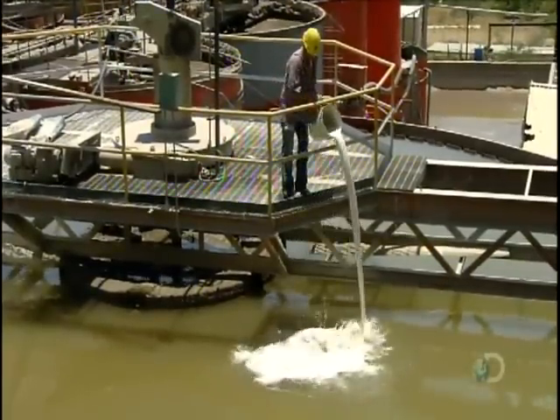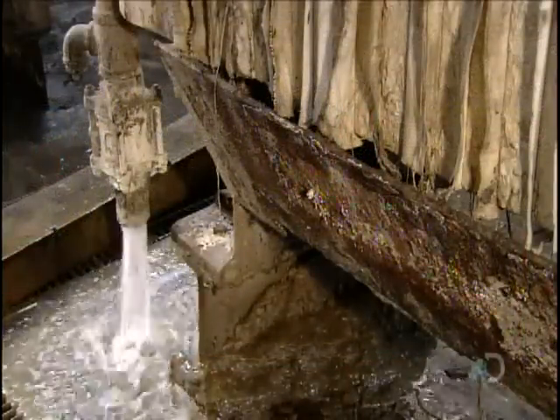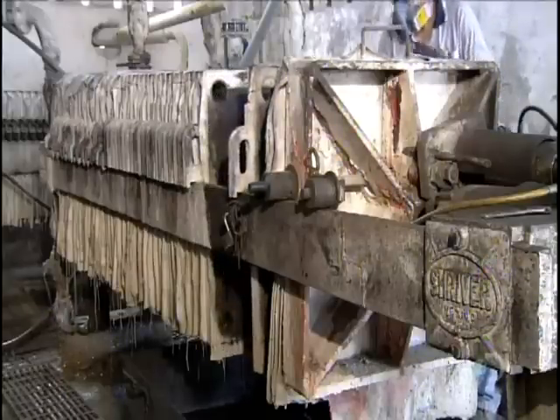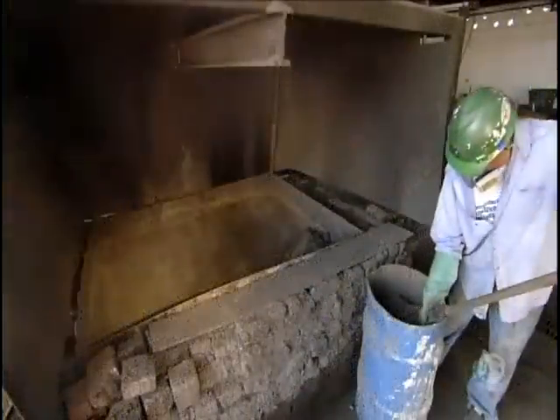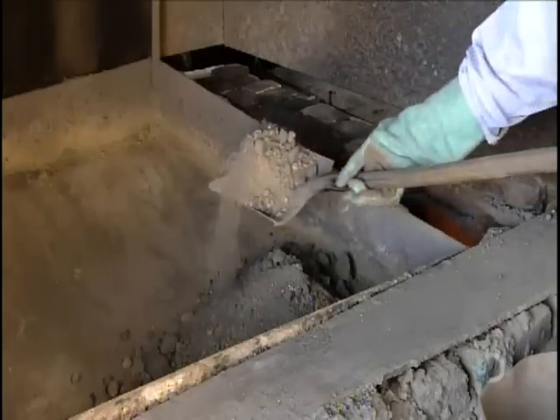72 hours later, the rock waste has settled at the bottom, and the solution containing dissolved silver is pumped through filter presses. The filter plates are treated with a zinc-based chemical which attracts silver molecules. As the solution passes through, the plates trap particles containing silver, forming a layer of black powder called silver precipitate. This precipitate is composed of approximately 50% silver and 50% waste — the waste being a jumble of various metals, dirt, and other impurities.